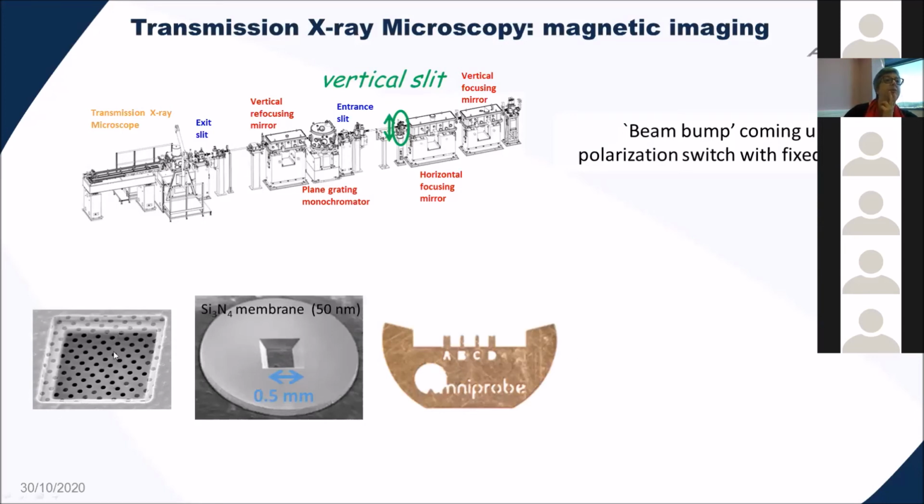The typical substrates that one uses can be the same ones used for biosamples, so typical TEM grids with a thin polycarbon film, quantifoil, whatever. Very often silicon nitride membranes for flat samples, for multi-layers and so on. And one can even use this kind of omniprobe holders made for 3D objects, where they are totally freestanding within vacuum then.